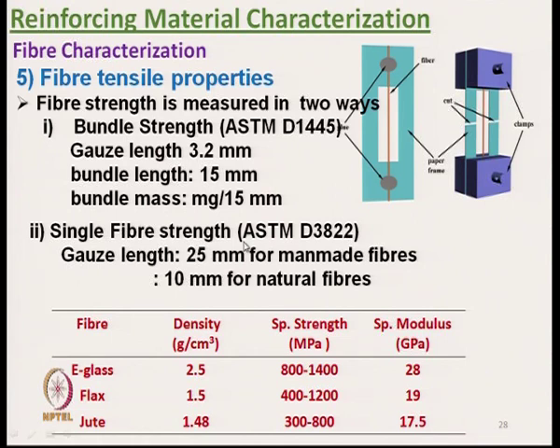And in addition to the bundle strength, we can also perform the single fiber strength test. And the gauge length here is 25 mm for man-made fiber and 10 mm for natural fiber.